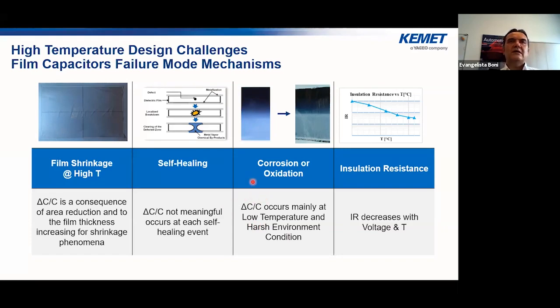Here we can see, from the KEMET point of view, the most important part of this presentation is the main failure mode mechanisms of the current KEMET series working at high temperature. One or two years ago, it was thought that the decreasing performance of the polypropylene film, the main film used in resonant and power box capacitors, was the main cause of the poor endurance test results at 125 degrees of the current series. But in the end, thanks to deep analysis made by KEMET on the root causes, we identified that the real root causes can be a little different, and can be addressed. For this reason, we were able to develop such a new series.